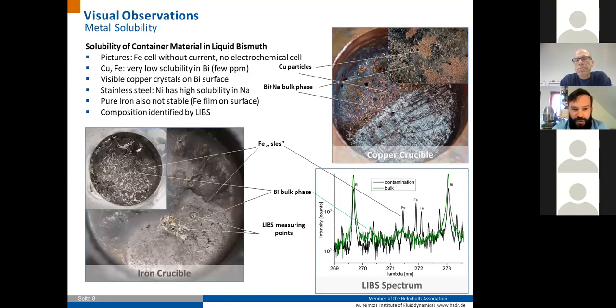The mentioned impurities can be quite disturbing for doing such experiments. Here you can see two different early experiments with different crucibles. On the upper right side, a copper crucible was used. And as you can see, this cell was a bismuth sodium cell.